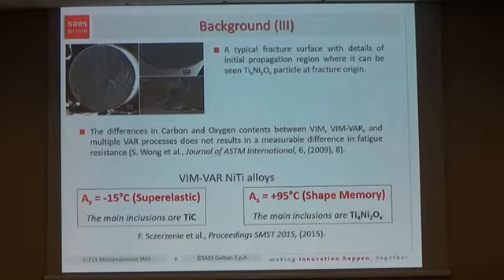Most of the people look at the gas impurity level to say something about inclusions. But the carbon and oxygen content between different melting approaches, typically used by melters, and I talk about commercially available materials, does not result in a measurable difference in fatigue resistance. And that's one other important point we will get back to in a few minutes. So looking at the carbon and oxygen is not conclusive about the inclusion size, the area fractions, the effects on fatigue.